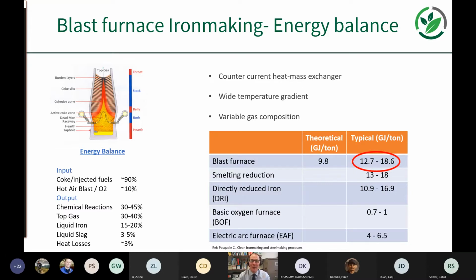So solid raw materials, coke, iron ore, fluxes are charged at the top of the furnace, and then you've got a heated blast of air that's directed in from the bottom of the furnace. So the highest temperatures are at the bottom of the furnace. They're typically raceway adiabatic flame temperatures in the region of 2,200, and then at the top of the furnace you've got temperatures that are closer to 100, and most of the energy comes from this carbon-based coke or injected reductants, like I've been involved with, injected coal. So compared to the other technologies, the specific energy, gigajoules per ton, is highest for the blast furnace.